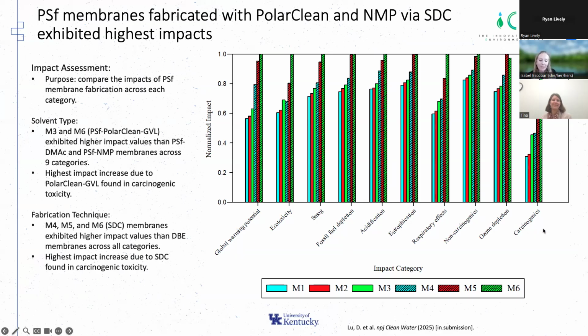And one of the issues is the viscosity. The higher viscosity necessitates a higher amount of the green solvent in order to reach that steady state in the fabrication as compared to the other membranes, as compared to pure NMP and DMAC, which are very low viscosity. So this was surprising to us. It was surprising to us that across the board, the green solvents actually came out to be undesirable.